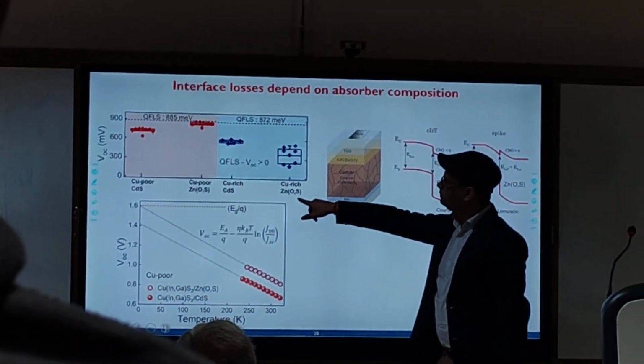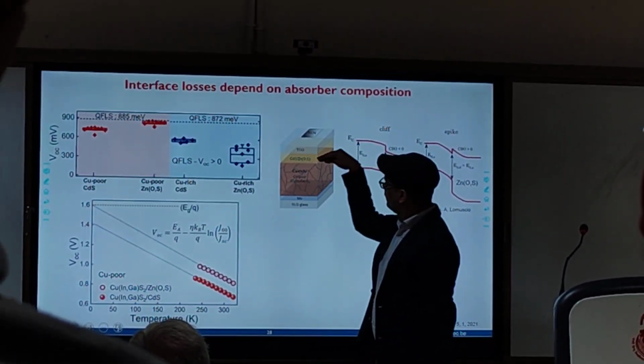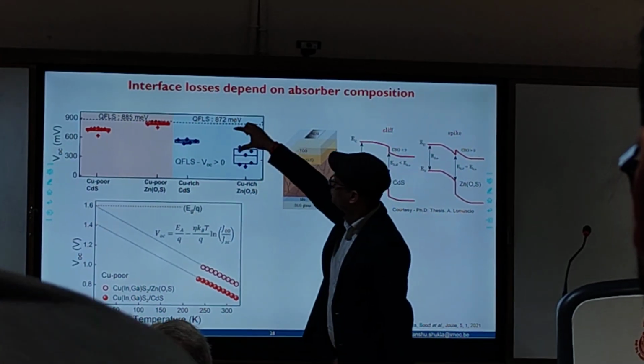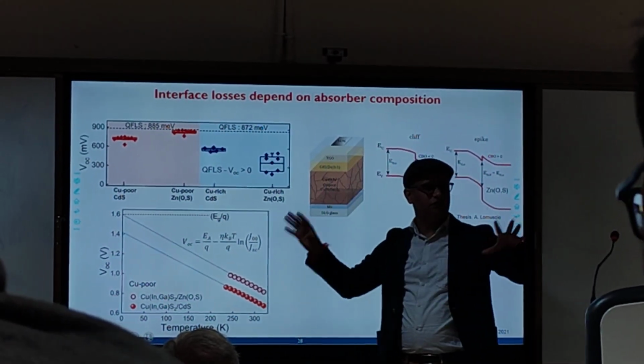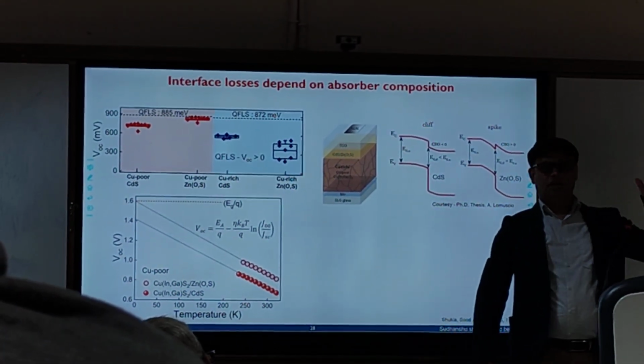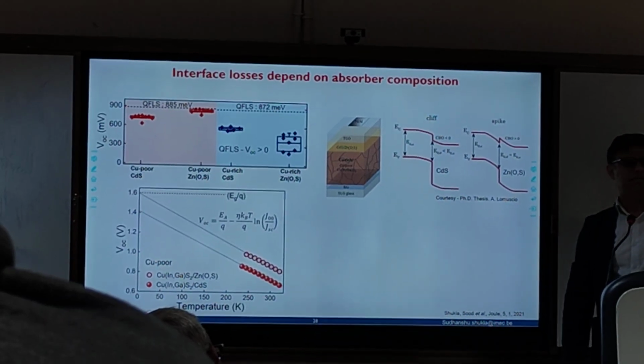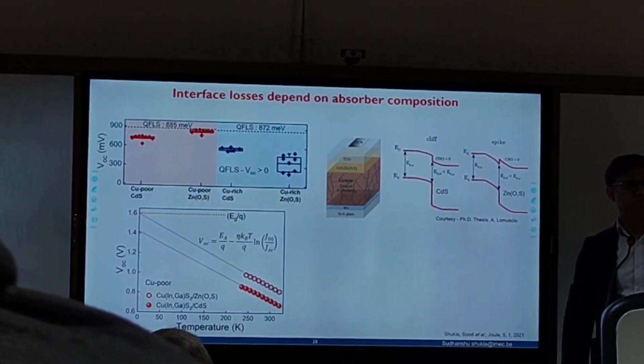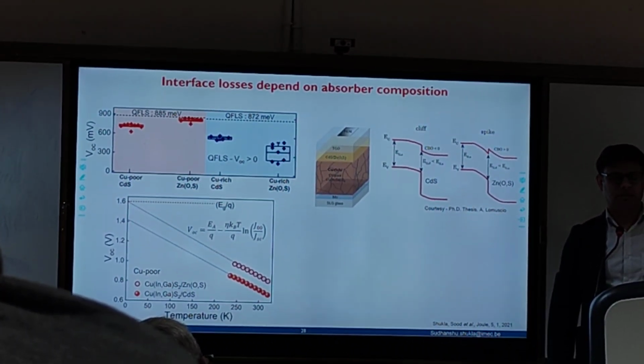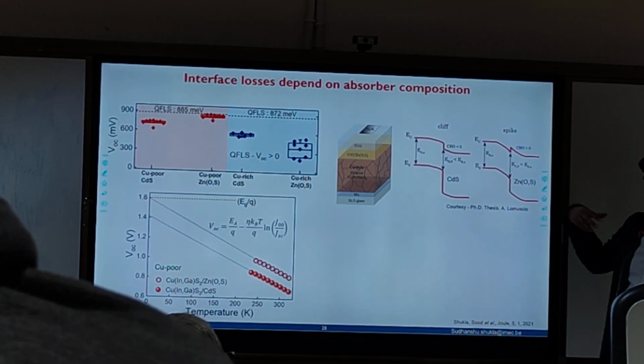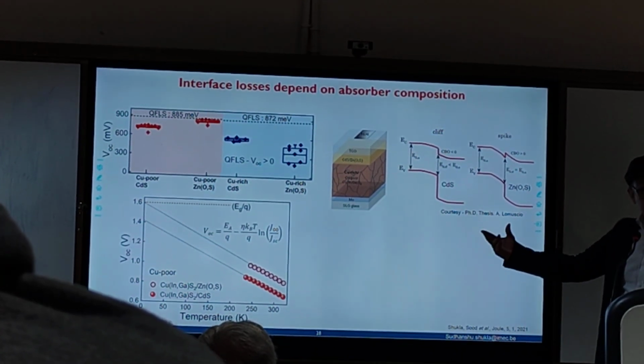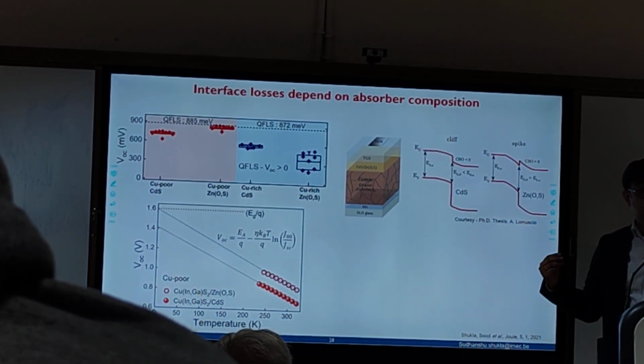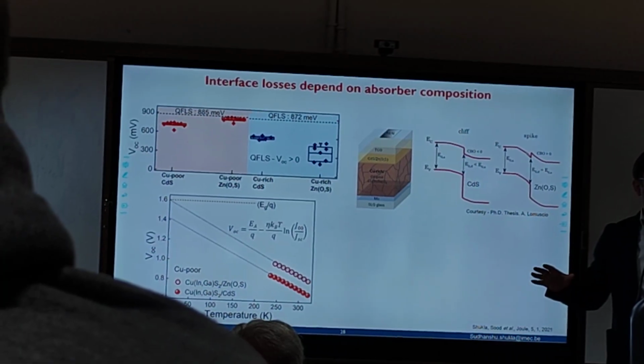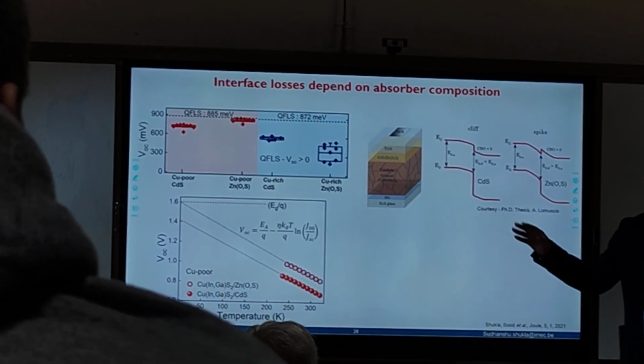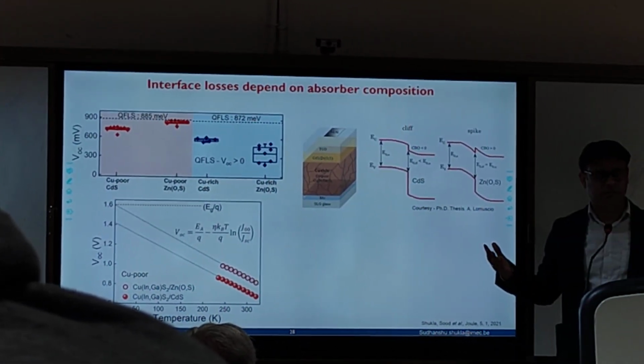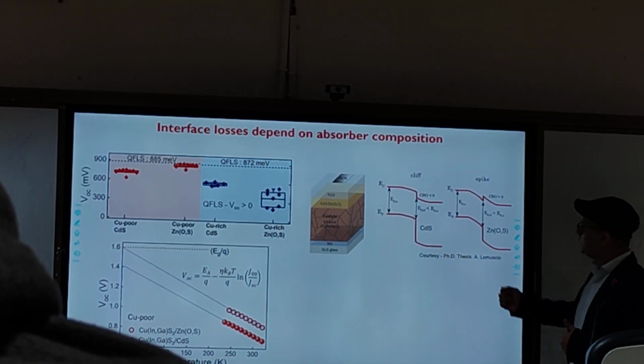Same thing in copper rich, if you see, with cadmium sulfide and with zinc oxysulfide, both show a difference. So there is interface recombination all the time. Which means copper rich CIGS sample is always dominated by interface recombination. And this tells us that the copper rich CIGS surface has some defect which you cannot get rid of. There is something peculiar to copper rich stoichiometry which we don't understand.